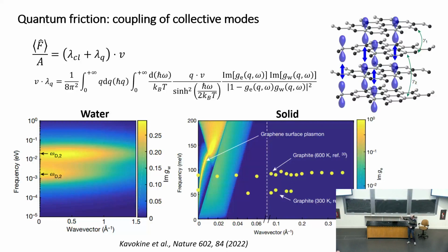They compare very well with the excitation frequencies in water, and so this proximity suggests that water can relax momentum into electronic excitations in graphite very easily, versus in graphene, where there is not a lot to couple with, because this mode here disperses a lot, and then there's nothing more to couple with.